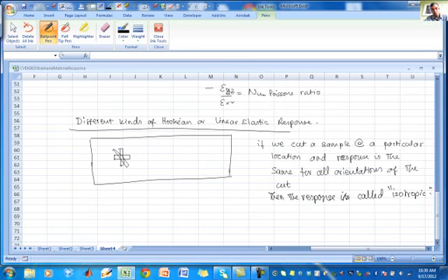By the way, one word of caution. This depends upon how many tests you do and how accurately you do the tests. So this is not a material property, it is a property of the model, because if I did a crude test, maybe it looks like it doesn't matter which way I cut the sample.